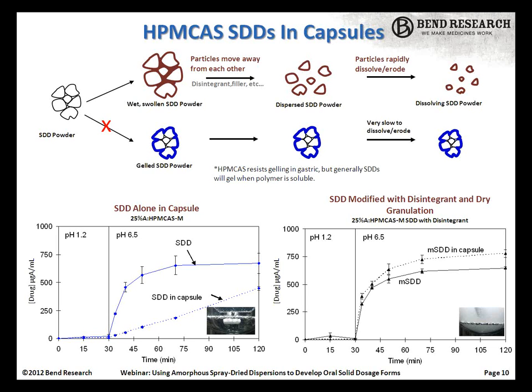What you can see in the graph in the lower left is a two-stage dissolution test where the material is placed into gastric media at pH 1.2 and then is there for a half hour and then transferred over. The solid blue line is the SDD controlled as made as a suspension, whereas the dashed line is a capsule that was just placed into the USP dissolution vessel. And you can see a much slower dissolution performance here. And this slower dissolution performance would transfer over to potentially not gaining the advantage in vivo.